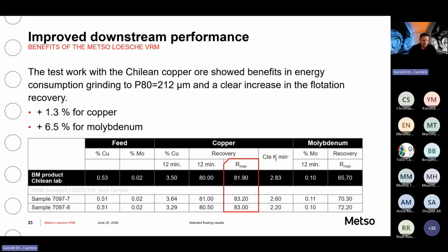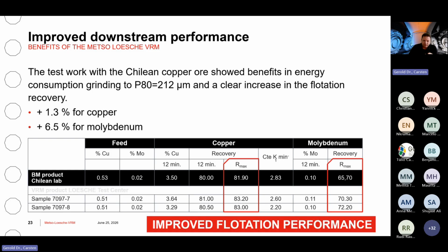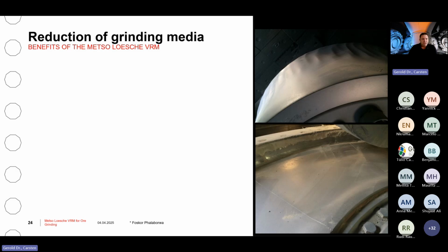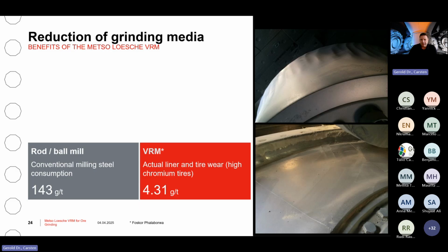Molybdenum is a very soft metal. And usually in the ball mill, it tends to be overground and then it starts to smear. But because we directly classify it out, we could highly increase the molybdenum recovery. So this is something that we often see, depending on the element, sometimes stronger, sometimes weaker, but we often see improved flotation performance.